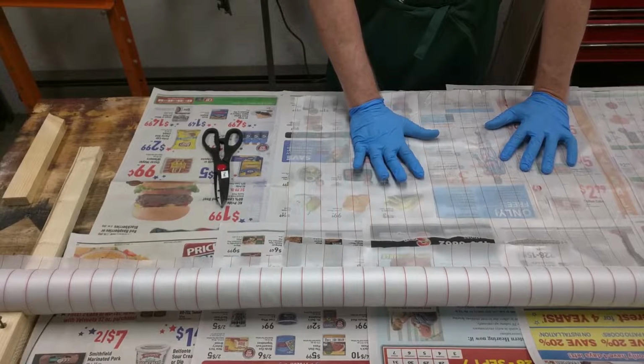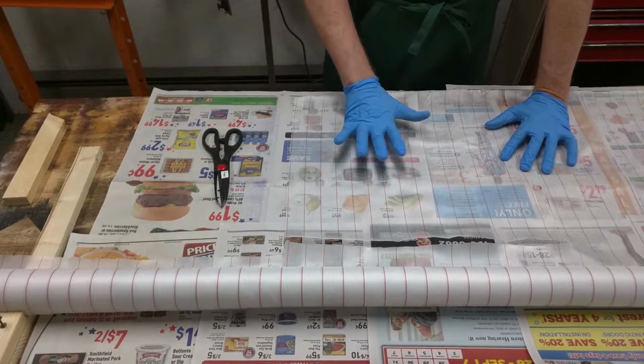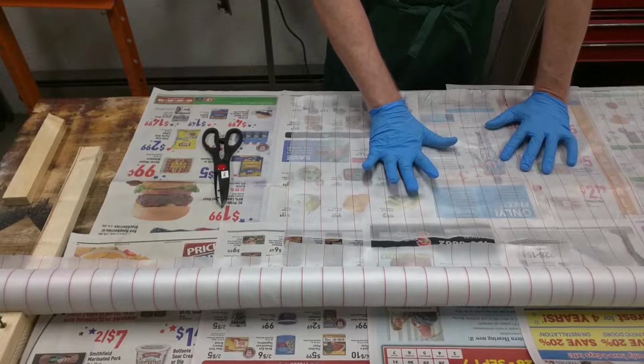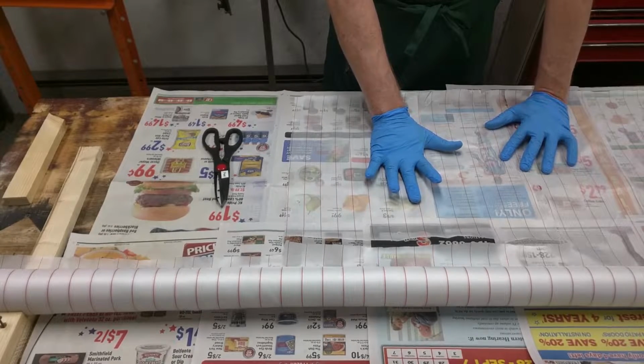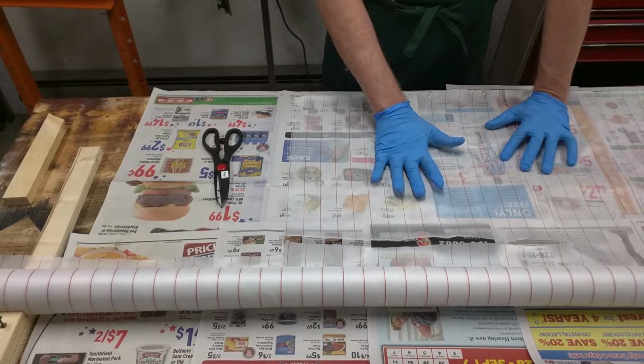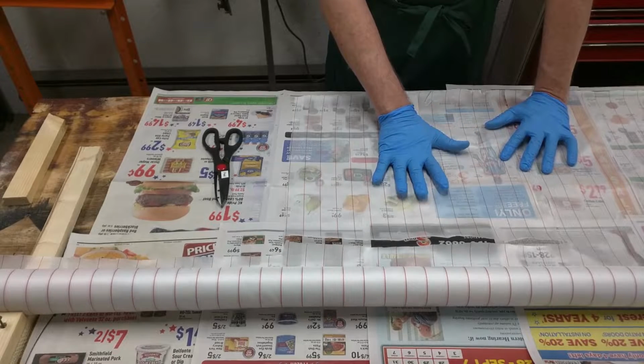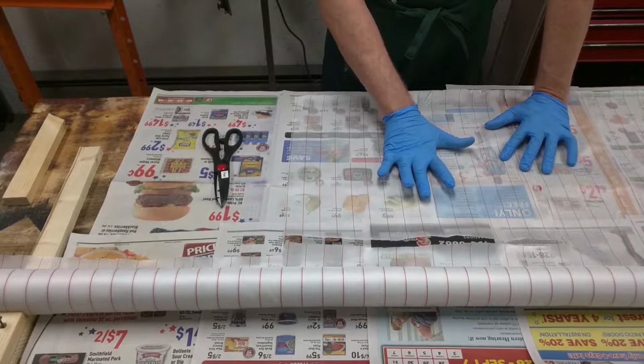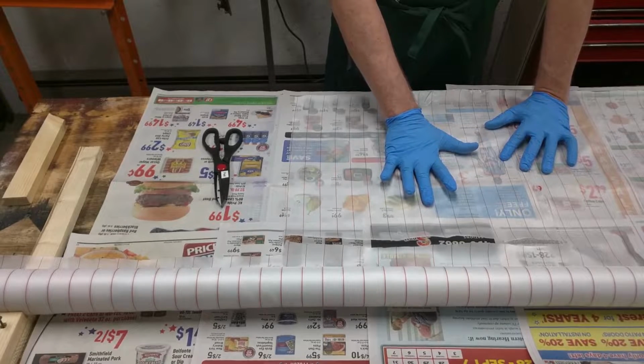Another reason for peel ply is that if we wanted to use adhesive to glue something to our carbon fiber, let's say another piece of carbon fiber, this peel ply, after we peel it off, will leave a rough surface that makes it easier for adhesive to make a good mechanical bond between our 2 pieces.